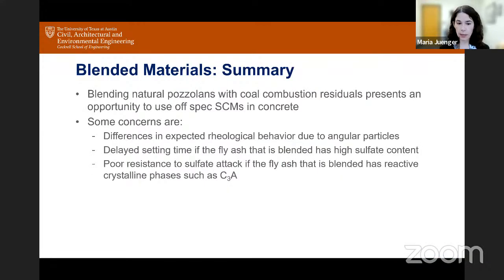So I think we have a lot of opportunity to start blending and mixing materials, not just natural Pozzolans, but even inert materials with coal combustion materials and other products to expand our resources of what we're using, and take advantage of everything available. But we have to be careful with rheological behavior. We have to be careful with the sulfate content and the C3A content, which may necessitate changing specifications to demand X-ray diffraction, which in the US in C618, they do not currently require. So it's something to think about moving forward.